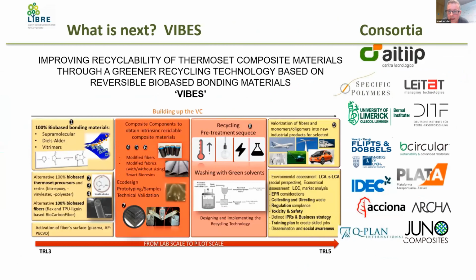So what's next? We're currently in a new project, a new Horizon 2020 project on recycling composite materials. We're looking at bio-based epoxies, but not the bio-based epoxies that you get off the shelf, which are about 30% bio-based. These are fully bio-based epoxies. We're recycling these epoxies by using a reversible cross-linking technique. The key thing here is that any bio-epoxies now are based on synthetic cross-linking chemistries, but the ones that we're producing are based on fully bio-based cross-linking technologies, and they can uncross-link on demand. So you can trigger cross-linking, and it makes recycling a lot easier.